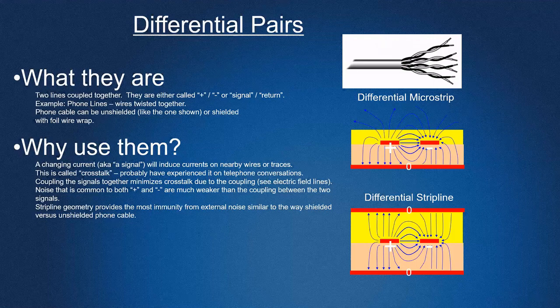Differential stripline. With differential pairs and stripline, a very common structure in rigid flex is to have a three-layer flex area where you have your reference planes on both sides, coverlay on top of the reference plane, and then the signal traces inside, the differential pairs inside. And you'll have a coverlay on top, but the coverlay is not electrically active in a situation like that because it's outside of the reference planes.